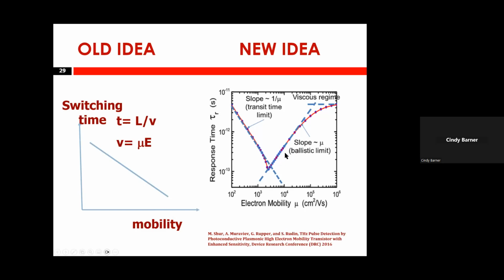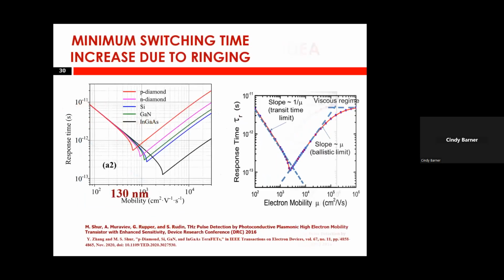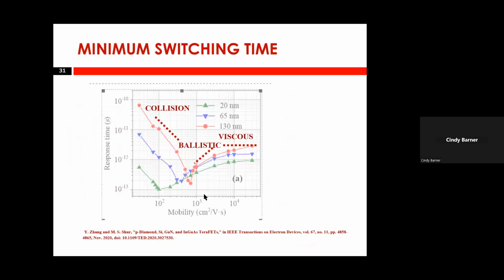So in fact, with very high mobility, you predict that because of this wave-like behavior, this switching time will increase and the cutoff frequency will decrease until you get to this saturation, which is the so-called viscous regime, because electron fluid has also viscosity, just as conventional fluid has. And these are calculations that show that this effect could be very important even in devices as long as 130 nanometers. And this is another calculation for 20 nanometers, 65, 130. So this is extremely important effect.